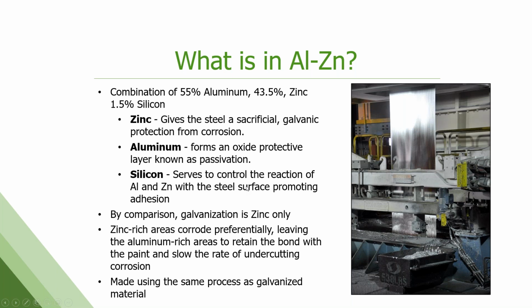So zinc is the sacrificial part, right? Anyone that's familiar with galvanized knows how this works. That galvanic reaction takes place. The zinc sacrifices itself to protect the steel. But as it does that, it wears off, right? You lose that zinc over time. The aluminum, however, forms a protective oxide, also called passivation, more of a barrier. It's fairly inert, so it stays around a lot longer than the zinc does.